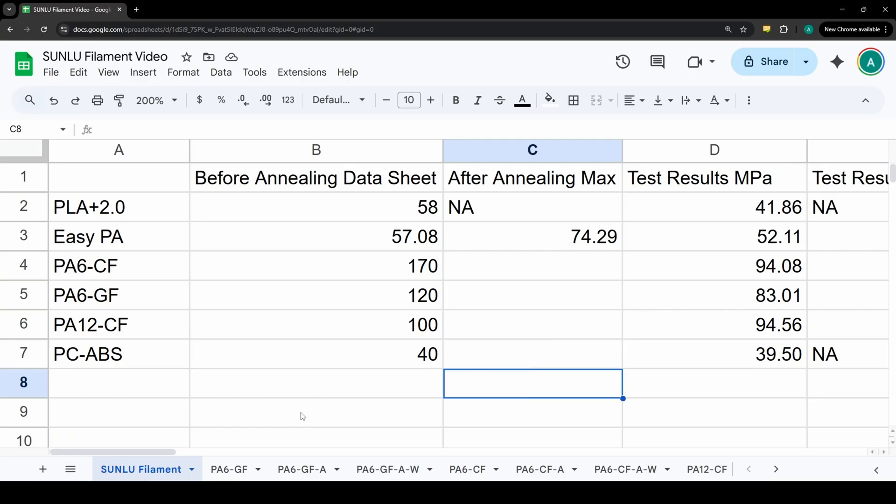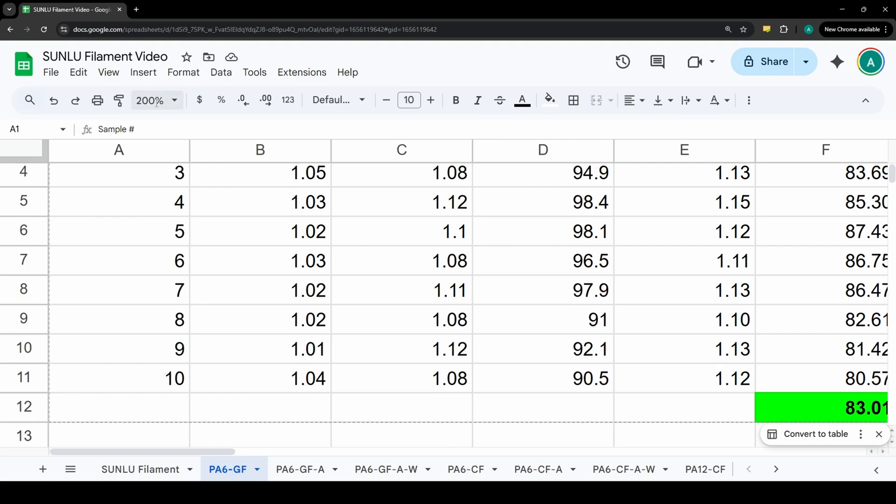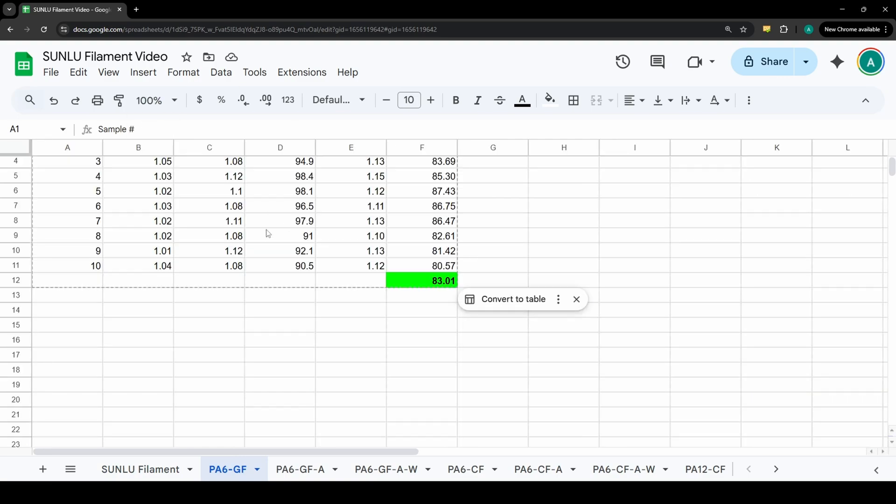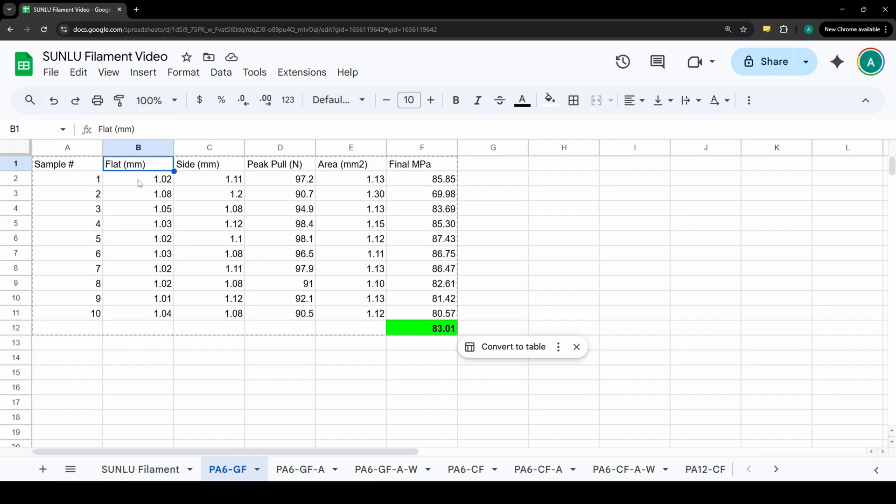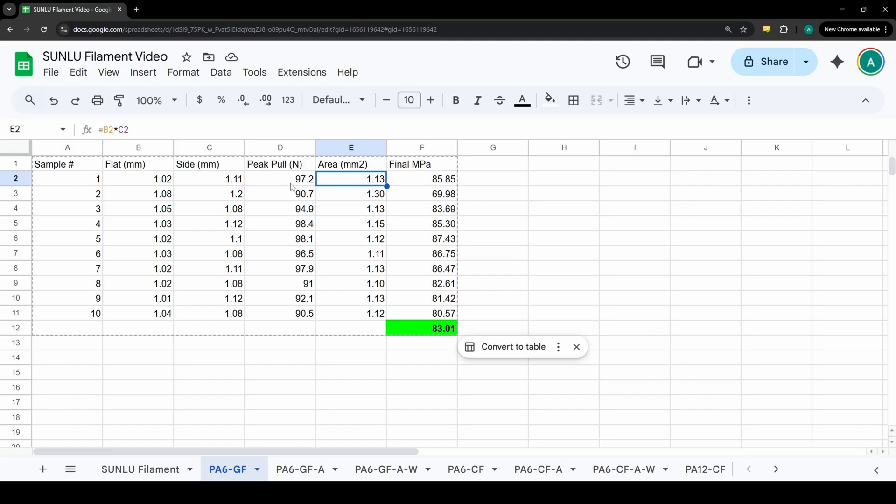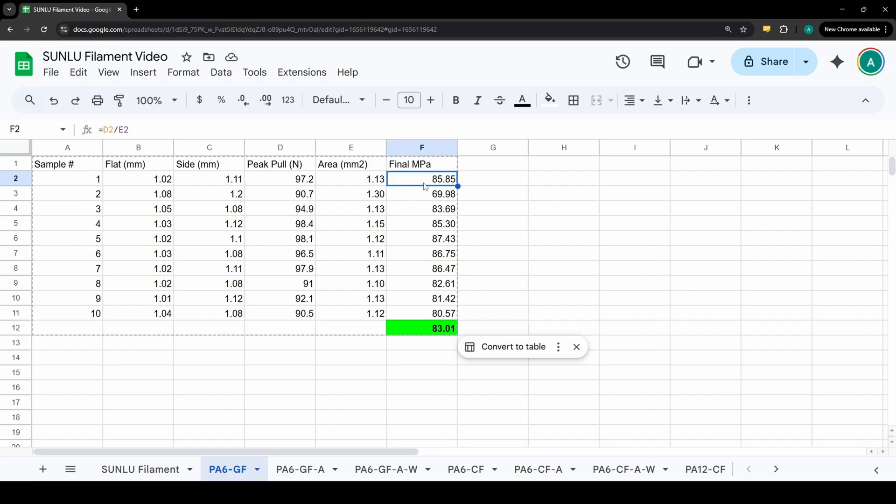Now that we have our first round of tests out of the way we can take a look at the data from the tables. Before doing every test I would measure both sides so that I could get the actual measured area and then I could adjust my peak pull measurement divided by the area to get the final MPa. So all of the measurements are an adjusted value from the actual test sample because I can't trust that they are actually one millimeter. I need to measure and adjust those measurements based on what the actual sample dimensions are.